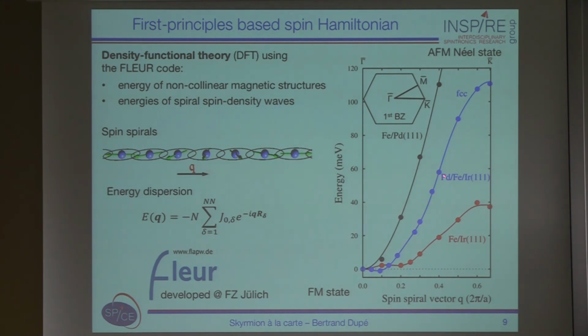And you have the case in the middle here, which is palladium, iron, iridium 111, where you put one palladium overlayer on top of this system, and you see that the dispersion curve changes quite dramatically, especially at this point. So here you destabilize the antiferromagnetic state. This energy now goes to around 110 meV, but you keep some kind of frustration close to the gamma point here, so you have a very flat start of the dispersion curve, and you even have here a small minimum